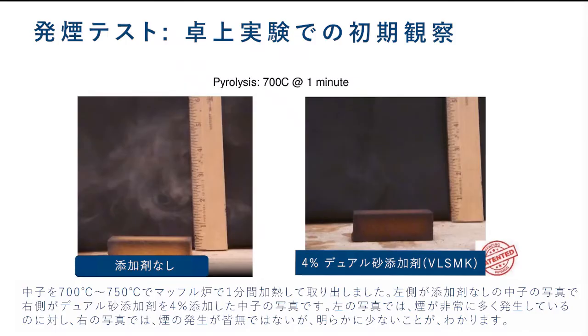So here's the first observation working with this engineered blend. If we want to look at how much smoke we are producing, the first experiment you do in the lab is to pyrolyze the cores. So we use a muffle furnace. We place the cores at around 700, 750 Celsius for about a minute. Then you take that core and place it on a ceramic bench platform. And as you can see on these two photos, these are actually photos from a video that we made.